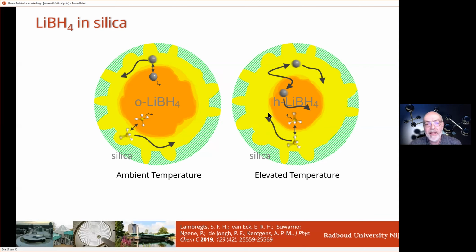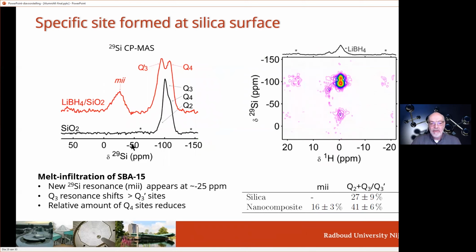And only at elevated temperatures, when we go above the phase transition temperature of the lithium borohydride, also lithium and borohydride start to move in this solid phase. And then there is free exchange of lithium and BH4 units between these two phases. But already here, we have material that can conduct lithium extremely efficiently. So then we ask ourselves, why is that? Why do we get this liquid shell?